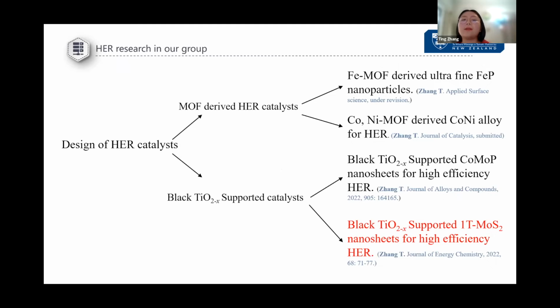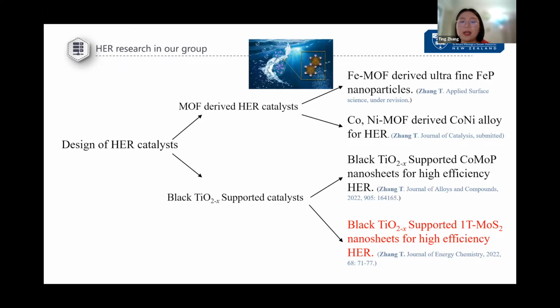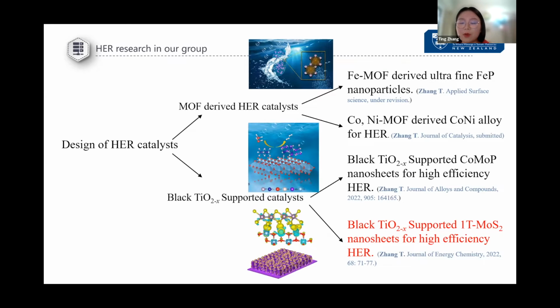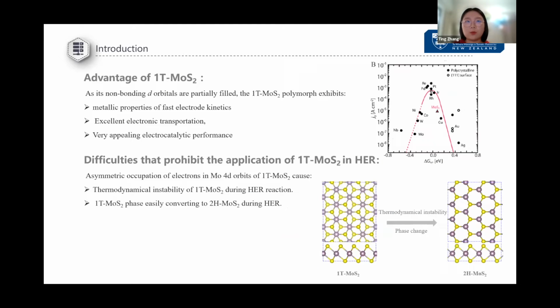There are two main research areas in our group. One is the MOF HER catalyst, and the other is the black titanium dioxide supported catalyst. Today, I'm going to introduce the latter, the black titanium dioxide supported 1T-MoS2 nanosheet for high efficiency HER. As shown in the volcano plot I introduced before, MoS2 is a material which has really high HER activity, and it has been recognized as a replacement for platinum in electrocatalytic hydrogen production. There are actually two phases in MoS2.